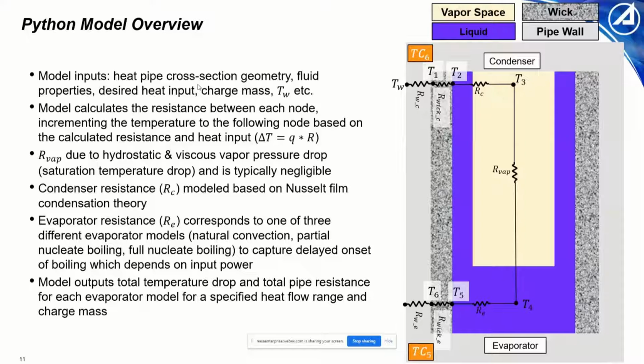A few of the more important resistances: the vapor pressure drop resistance, or hydrostatic and viscous vapor pressure drop, is typically negligible, normally modeled as a short circuit. Here we include it, but we also measured that the resistance value was orders of magnitude smaller than others. The condenser resistance is modeled based on simple Nusselt film condensation theory for a thermosiphon, basically.